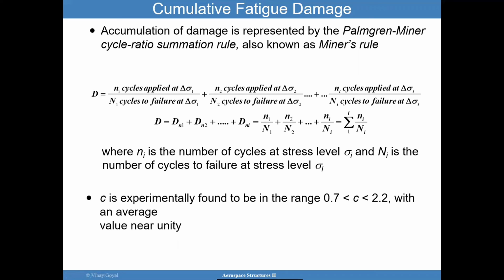That's a general approach. Experimentally, it was found that when testing was done, this value D actually came out between 0.7 and 2.2, but on average, it was about 1. So again, there are some difficulties here that decrease your confidence, because you wonder what value is going to hit. So one approach is to apply a factor of safety on this damage, and that factor typically tends to be 4.